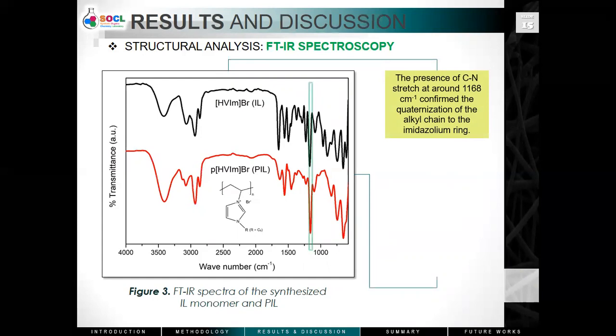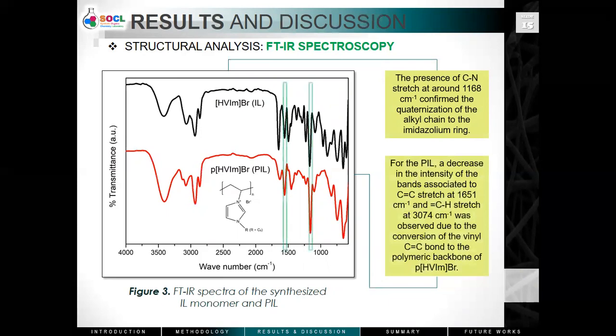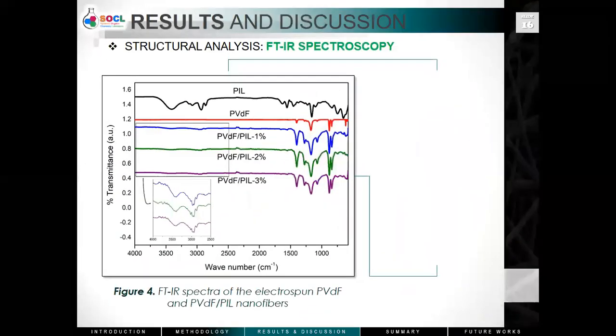Meanwhile, for the PIL, a decrease in the intensity of the bands associated to carbon-carbon double bond and C-H stretch was observed due to the conversion of the vinyl carbon-carbon double bond to the polymeric backbone of the polyionic liquid. Nonetheless, these bands were still present due to the presence of carbon-carbon double bond in the imidazolium ring. The appearance of all expected functional groups sufficiently confirmed the synthesis of the target ionic liquid monomer and the polyionic liquid. The incorporation of the PIL to PVDF was verified using FTIR spectroscopy.